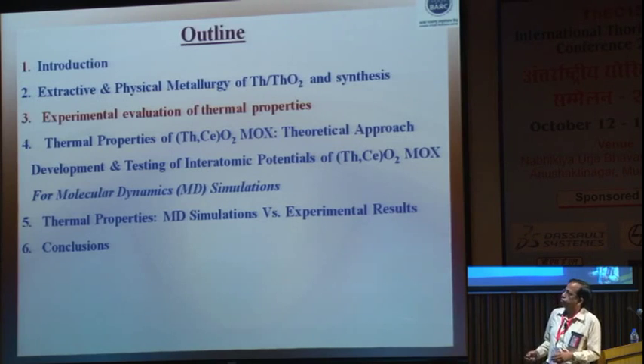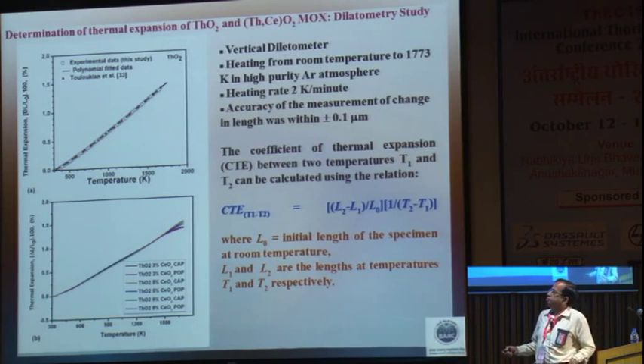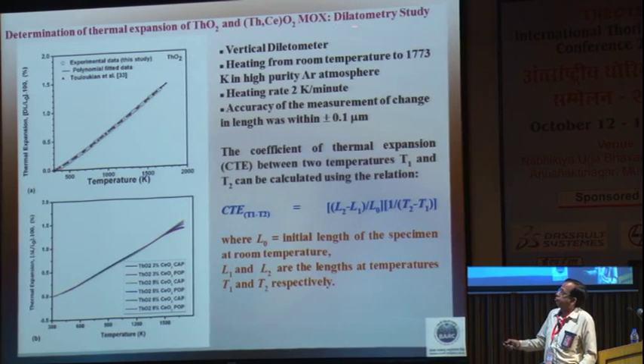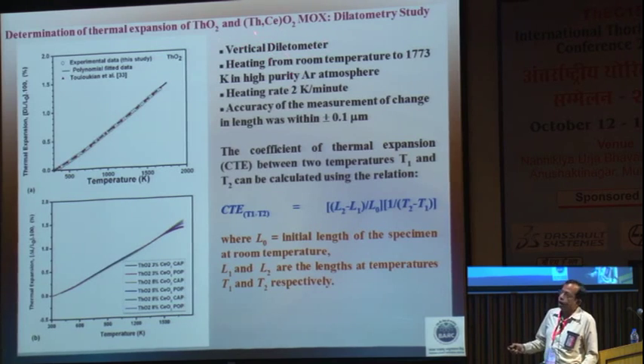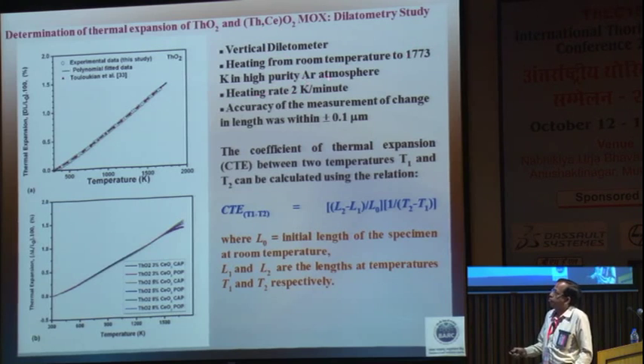So now coming to the evaluation of thermal properties experimentally, thermal properties like thermal expansion, for instance, have been estimated by dilatometry and X-ray diffraction. So this is a view of the dilatometry results. A vertical dilatometer has been used, and the heating rate from room temperature to this temperature in high purity argon atmosphere at this rate has been done. The accuracy of measurement is 0.1 micrometer.